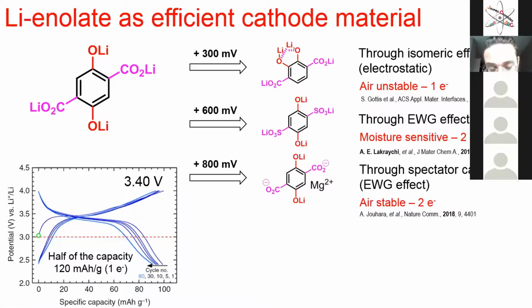But the problem with this molecule is that it shows only half of its capacity. It should have 250, or more than 200 milliampere hour per gram. Here it is showing only 100, so 120 milliampere hour per gram. So it's very, very low as compared to the theoretical value.